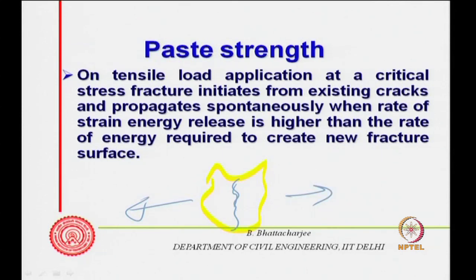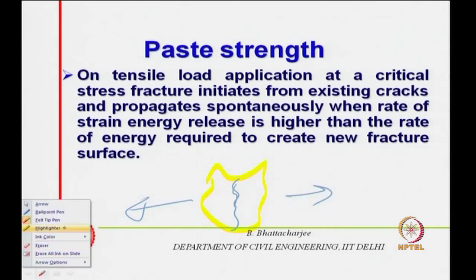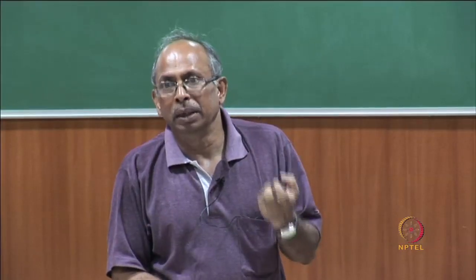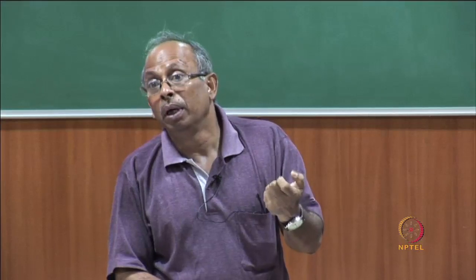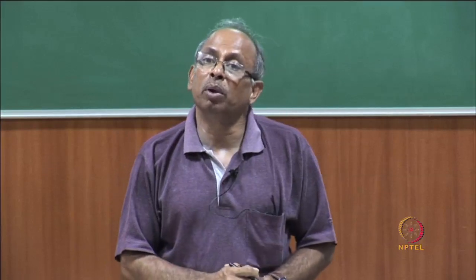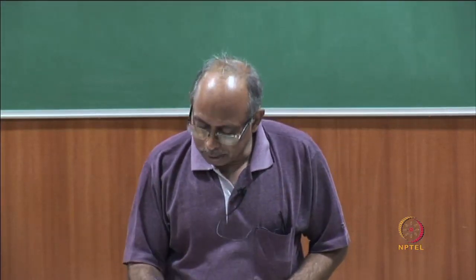Now, this separation means creating a new surface. So, you are creating a surface here and a new surface there, which is matching, of course. So, by pulling them apart, you have actually created two new surfaces. Now, each surface is associated with a kind of surface energy. There is an interface between solid and liquid, or solid and air. At the interface there is always some sort of energy associated with it, because the material here